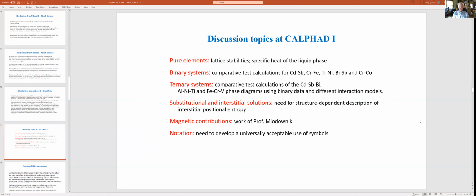We also supplied each other with data for ternary systems. And in this case, the systems were cadmium, antimony, bismuth, aluminium, nickel, titanium, and iron, chromium, vanadium. And with the data for the binaries that we supplied to each other, the aim was, what methods did we use to link the binary systems to obtain the thermodynamic properties of the ternary? And what effect did the methods we were using have on the subsequent calculated phase diagram? And the main interest here was to see which of the different interaction models gave, well, did they give very different results, or did they give similar results?